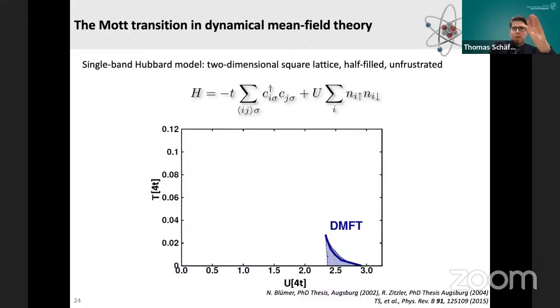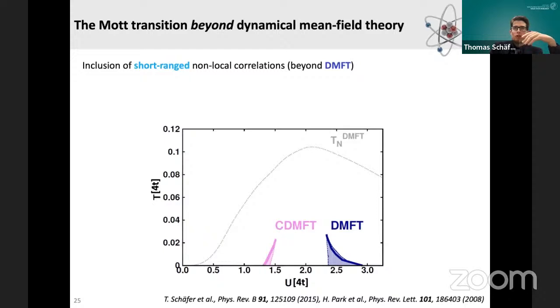So let's go back to our single-band Hubbard model calculation and see what the inclusion of spatial correlation does to it. Well, if we include short-range spatial correlations by means of this cellular dynamical mean field theory, we see two things happen. So this is now a finite size cluster of 2 by 2 lattice sites. First of all, the critical onset of the Mott-Hubbard transition is significantly reduced. So this means you need less Coulomb interaction in order to get an insulating state. Also, the coexistence region shrinks, and the shape of this curve is reversed.